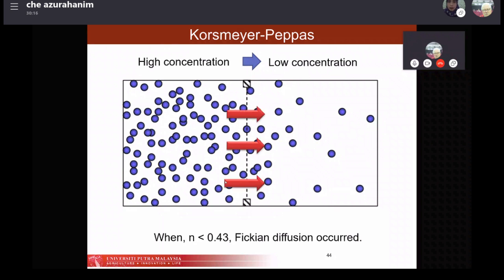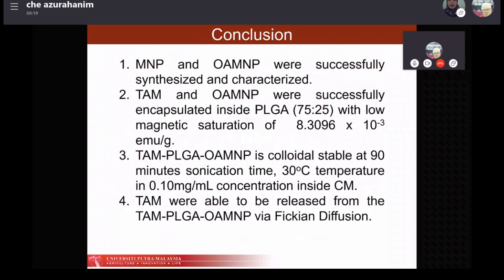So for the first project, the conclusion that can be made is that MNP and OA-MNP were successfully synthesized and characterized, and the anti-cancer drug tamoxifen and OA-MNP were successfully encapsulated inside PLGA 7525, but with low magnetic saturation. Then TAM PLGA OA-MNP is colloidally stable after 90 minutes of sonication, at 30 degrees Celsius, at 0.1 milligram per ml concentration inside complete culture media. Finally, TAM was able to be released from the TAM PLGA OA-MNP via Fickian diffusion.